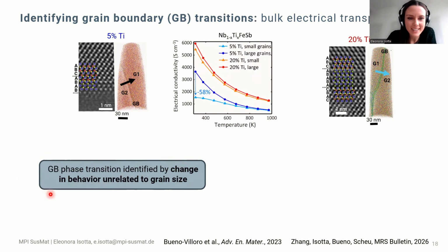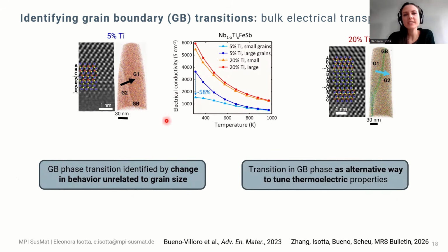So again, in this case, the change in electrical conductivity was not related to grain size, but was related to a change in the grain boundary phase. And this can point us to a very interesting direction, that the grain boundary phase appears to be an additional design method for the properties themselves.